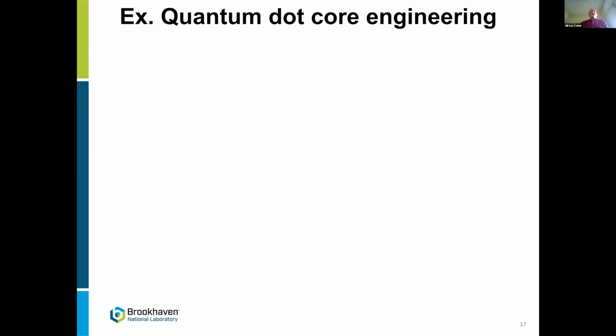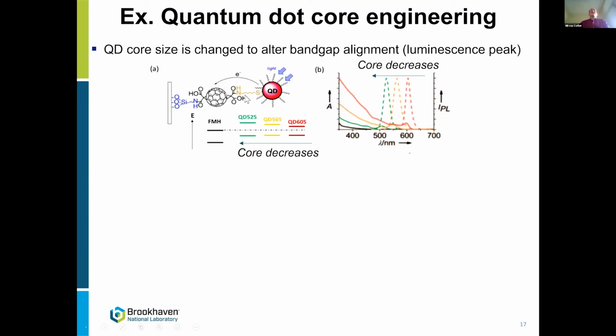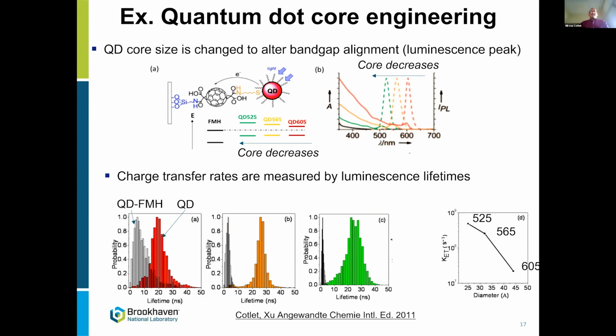One such example is we use quantum dot core engineering. In this particular case, we have quantum dots of varying size, like I said, and we vary the size of the quantum dots. We vary this band gap here. So from large to small quantum dots, we just increase the band gap. As a result of this manifestation, if you look here in the emission spectra of the quantum dots, we see that the decrease in the core size shifts the spectrum towards higher energy here. In these quantum dots, we use a molecular linker to attach a very good electron acceptor, fullerene. It's a derivative. So photoexcitation of the quantum dots is going to promote an electron into the fullerene. So measuring the quenching of the quantum dot in the presence of fullerene, we can basically quantify the strength of the electron transfer.